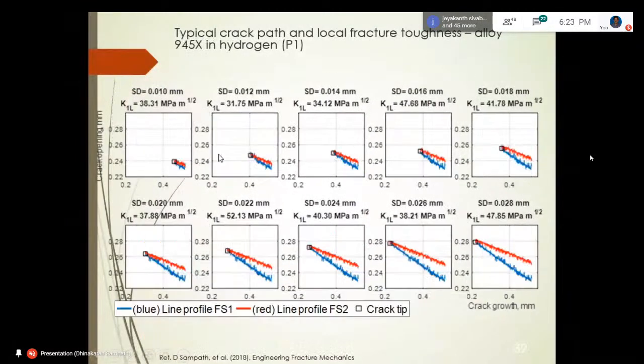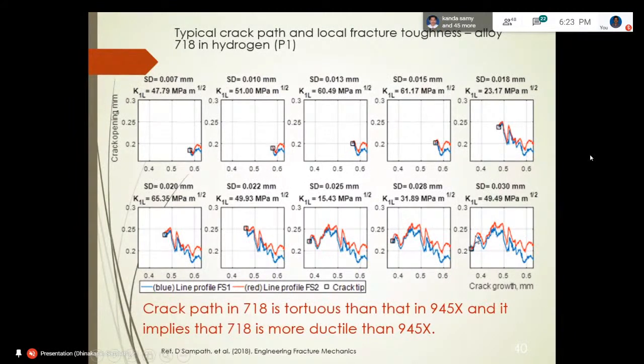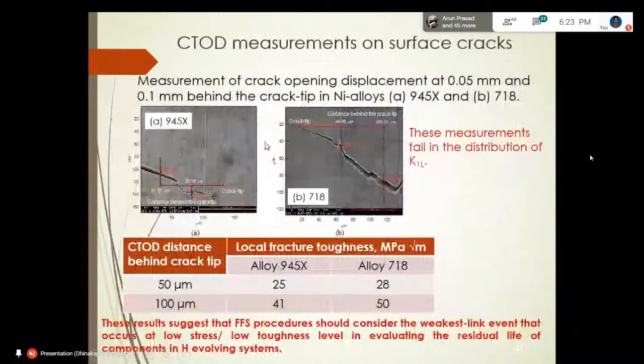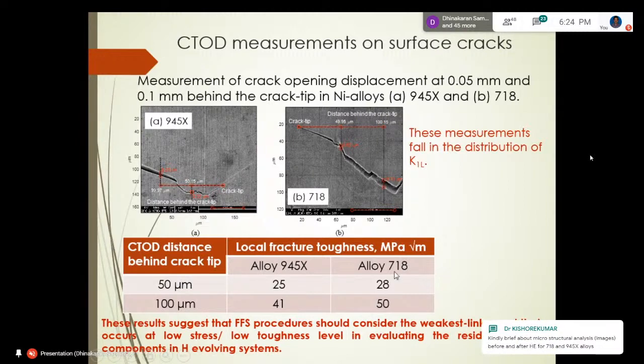For 945x we saw a very sharp crack, and for 718 we saw a tortuous crack. That means we have a lot of resistance to crack growth, because the load applied will be consumed in the interaction between the surface wake, the crack wake. And then to get some confirmation, we measured the crack tip opening displacement at the surface of the surface cracks on this specimen. This is the crack tip, and we measured at 0.05 millimeters and 0.1 millimeters, and then plugged that value into the equation for K, in local fracture toughness, and we got something like this.